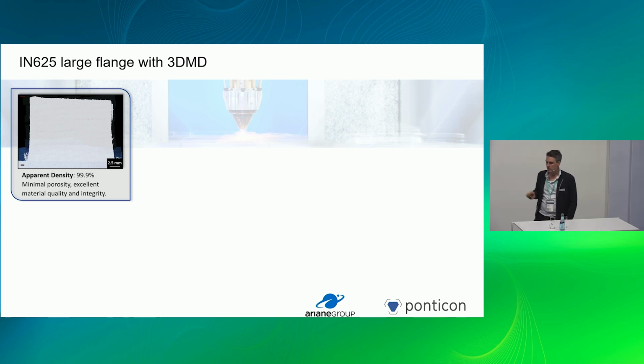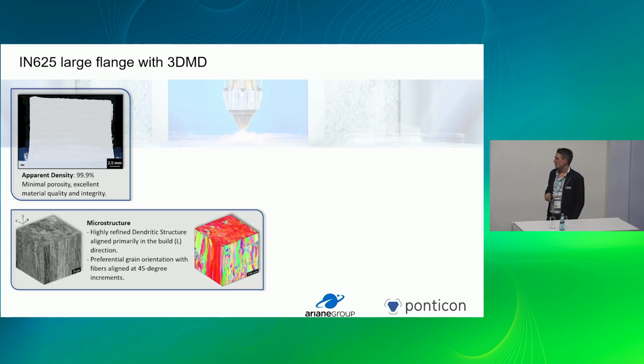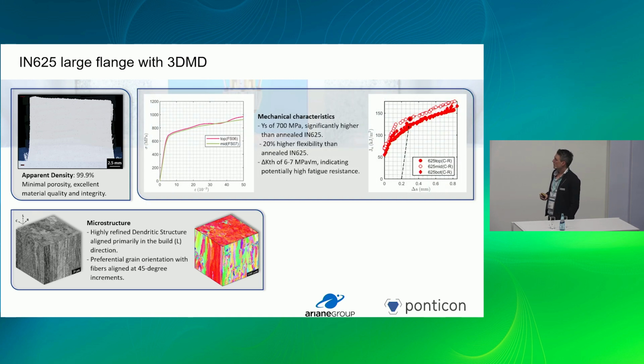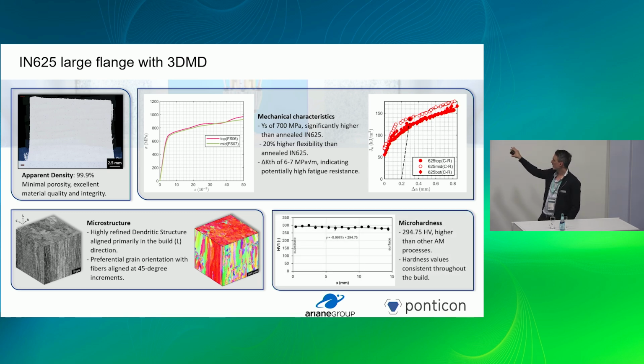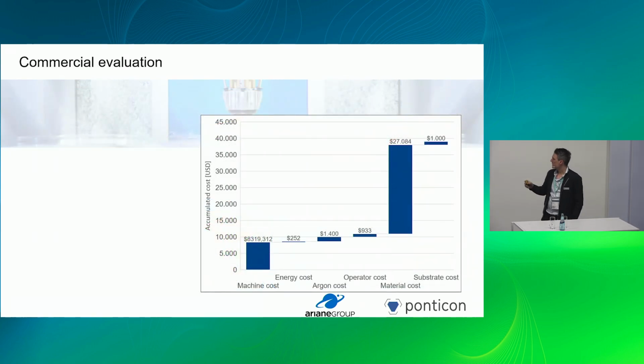So density of that part is close to 100%, that's fine. And in the microstructural analysis, we can nicely see the orientation of the grains inside the part. Some stress strain data, I don't want to get into the details of this. Just keep in mind it's as supposed to be, better than conventionally manufactured material, and definitely sufficient for the application that we're discussing. And adding to the crack growth and the stress strain, also some micro hardness evaluations. Essentially this is just the proof that what we're doing here performs the way it's supposed to. Of course it's important to pay attention to this, but I think we could successfully show that what we have does the trick for this specific application. I don't know why the image keeps disappearing, but doesn't matter.